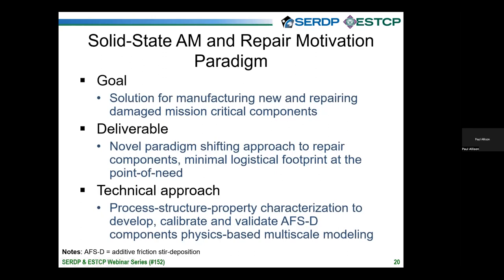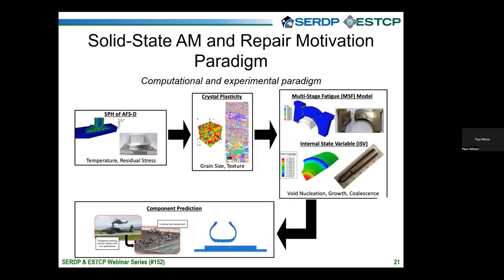We use smooth particle hydrodynamics modeling of the process, which allows us to tag particles to look at oxides or discrete strips of materials — not just monolithic feedstocks — and understand local plastic strains and temperatures during processing. This informs layer-by-layer heat inputs and process parameter control, and is coupled with microstructure-based multi-stage fatigue models and internal state variable plasticity damage models to capture both monotonic and cyclic behavior and understand component performance.